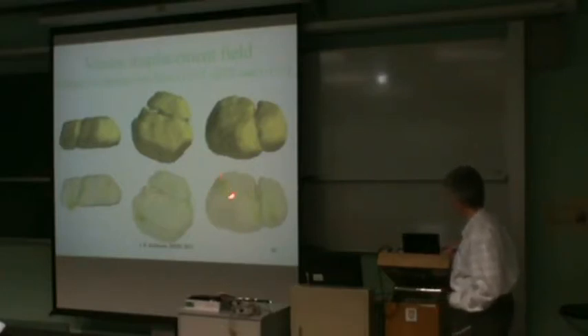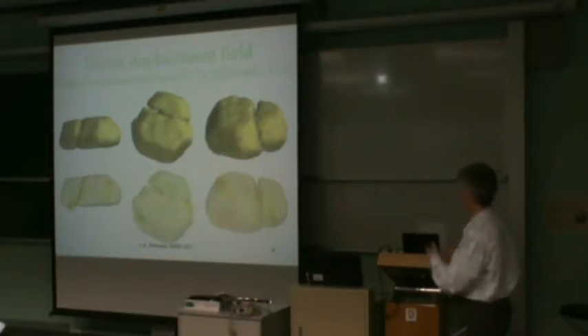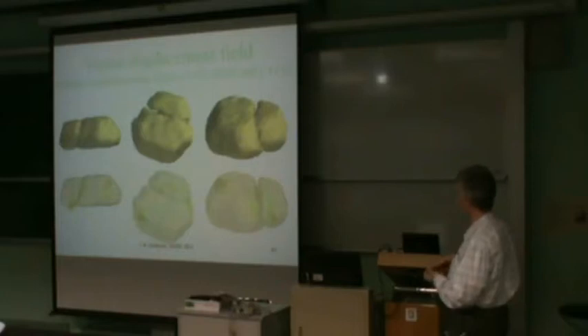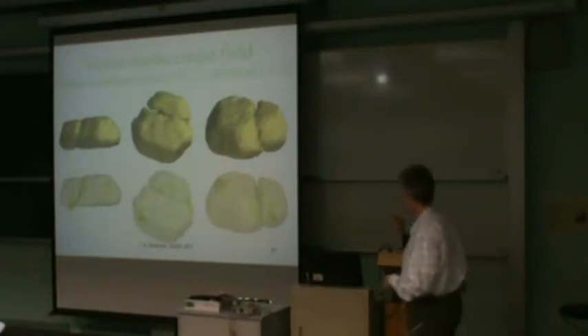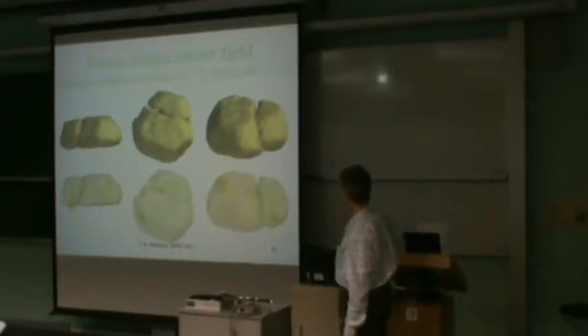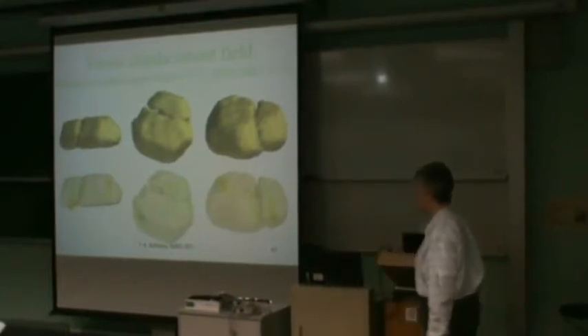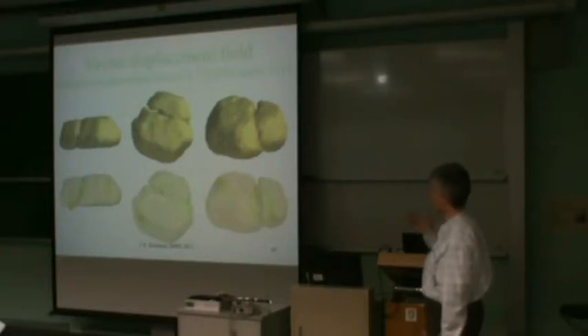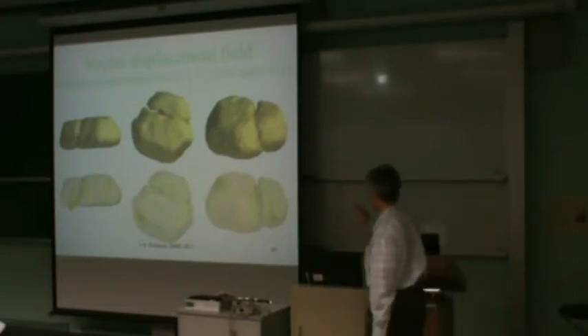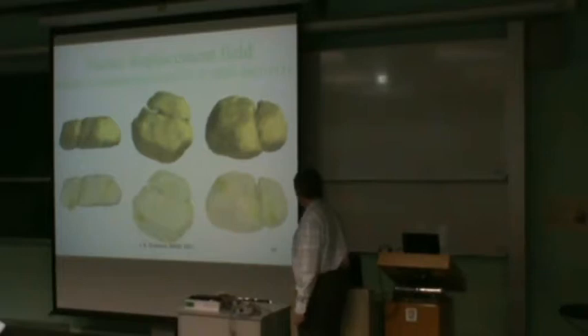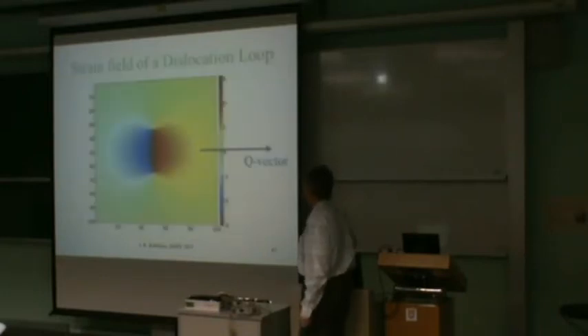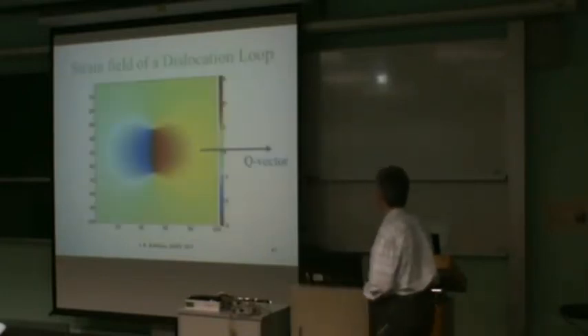And there's also something on the end that might be a surface deformation effect, where there's a strong concentration of strain that's appearing over there. But these are vectorial displacement measurements that have just been shown on the surface, because it's a 3-dimensional vector field that we've got, and there's a lot of information in it, but you can see the highlights of it here. So we get a lot of information about the gory details of the stacking faults themselves.